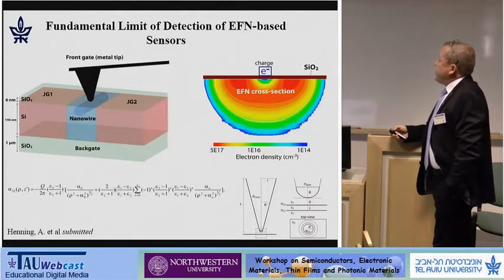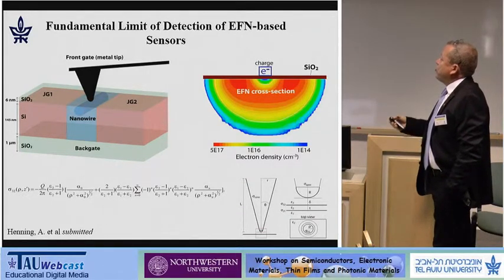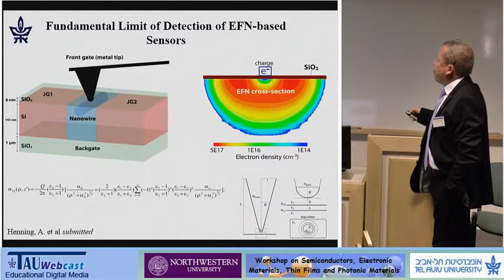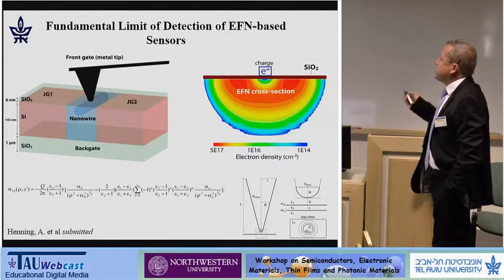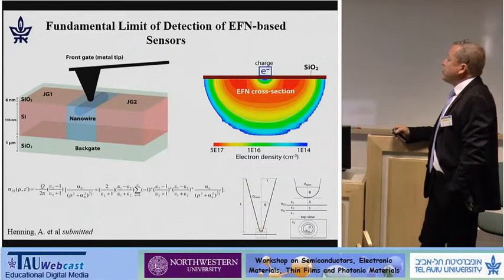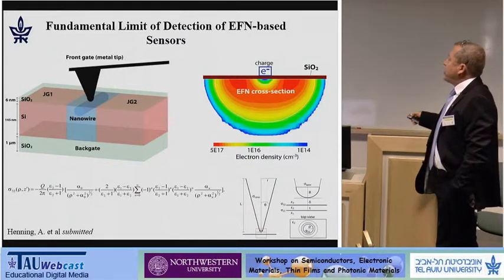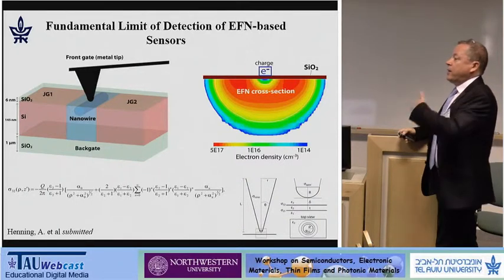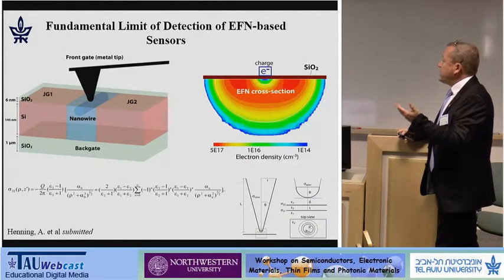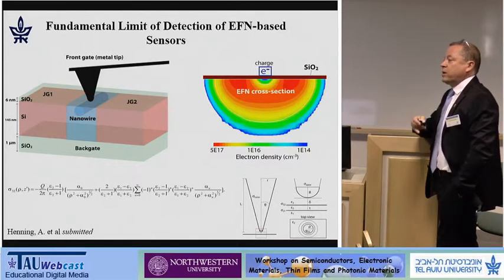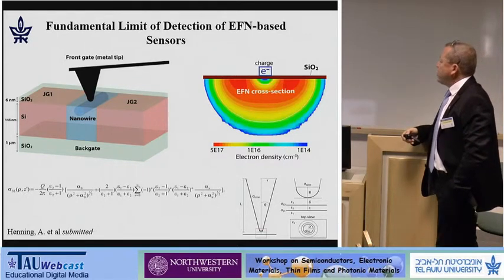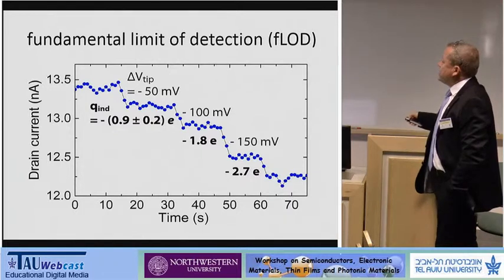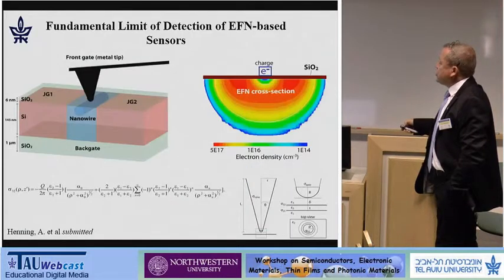Another very interesting thing is that we can emulate the effect of a charged molecule by a tip. We did a series of scanning gate microscopy. So instead of a charged molecule, we can come with a charged tip or tip with an applied bias and calculate the sensitivity of the devices. So by comparing the source drain current to simulations, we came out with a sensitivity of less than a single charge. What is shown here is the source drain current of such a device.